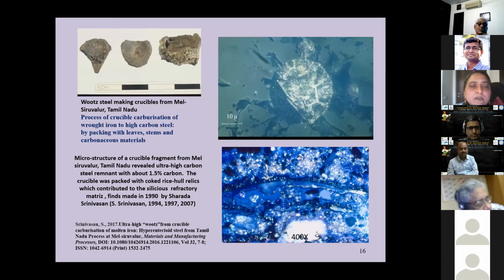And now I wanted to just point to some of the wootz making production sites which I had studied. One is from Mel-Siruvalur in Tamil Nadu. And so here, when you look at the microstructure, if you recall what I showed you in Pattinam, that's typical hypereutectoid wootz steel, a globule of hypereutectoid wootz steel, which is found in the matrix of this crucible, which I had analyzed during my field work, going back actually to 1990 when I found the site, which is also very important really to undertake field work and document and record these sites because they're all vanishing.